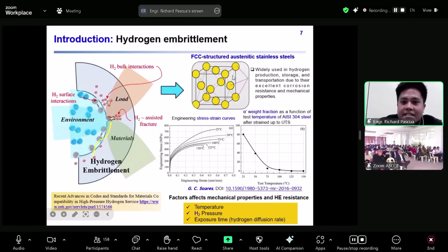Nowadays, austenitic stainless steel with an FCC, or face-centered cubic, structure is widely used in hydrogen services due to its excellent mechanical properties, particularly at lower temperatures. However, some studies have shown that this material can undergo phase transformation from austenite to martensite at lower temperature after straining. To evaluate the performance of this material under hydrogen environment, it is important to observe its mechanical behavior under several factors, such as temperature, hydrogen pressure, and exposure time or hydrogen diffusion rate.